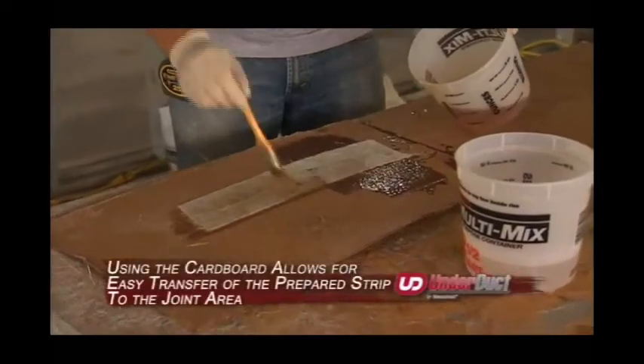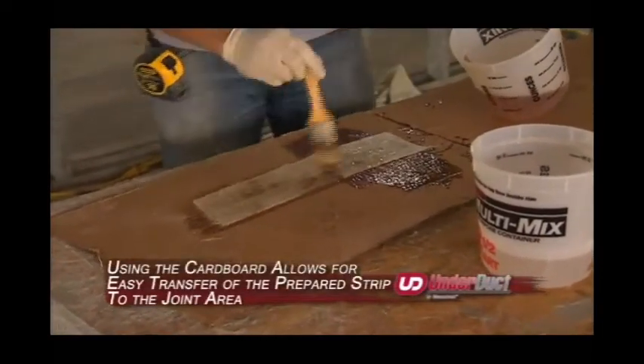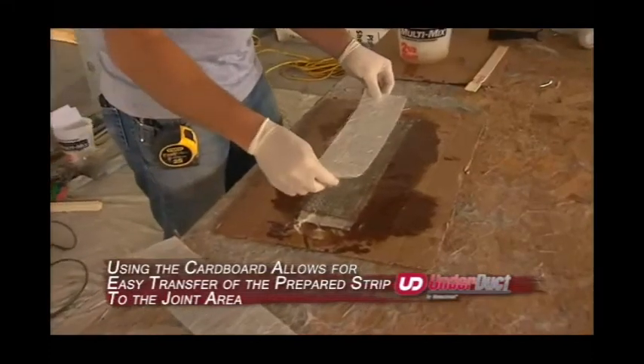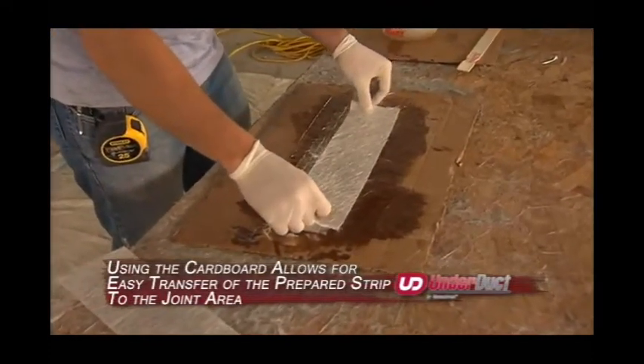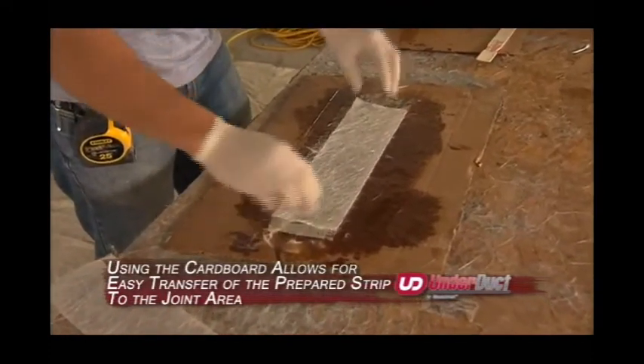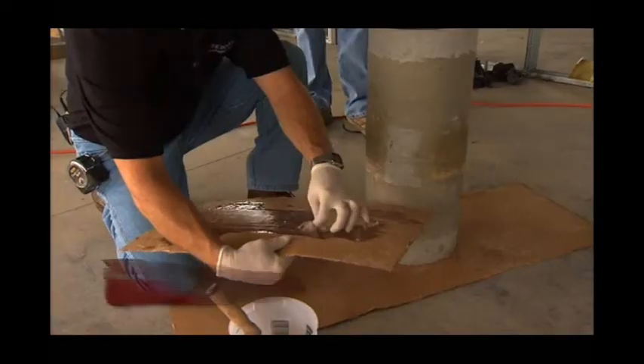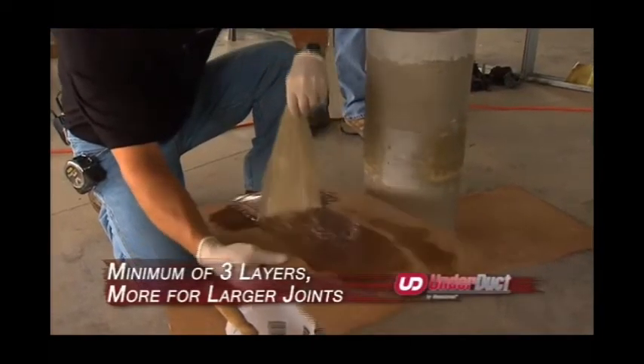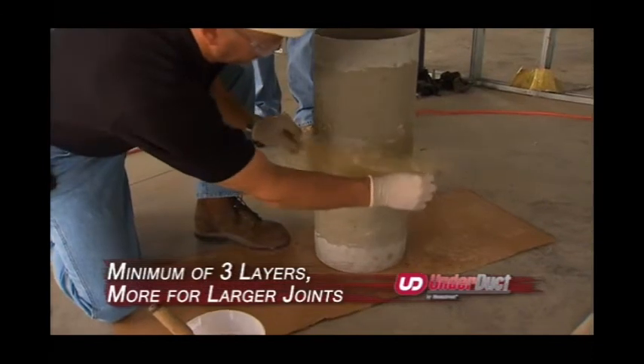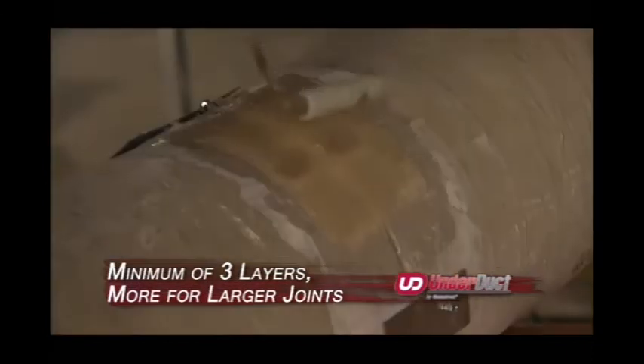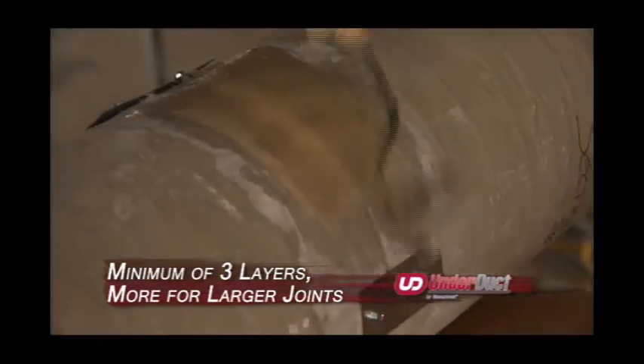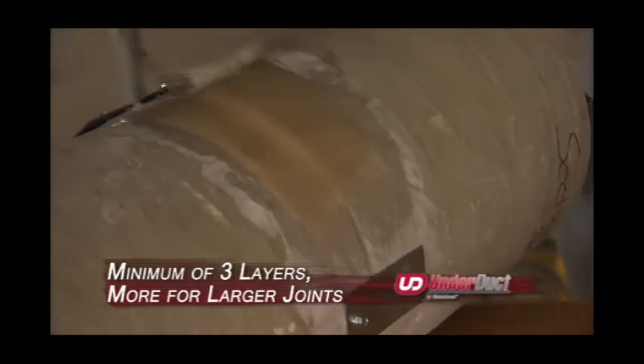Saturate 1 strip at a time on a pre-cut piece of cardboard, staggering the strips side to side and end to end until you have the recommended number of layers. Lift the completed weld strip or hot patch and apply to the pre-ground joint area. Using the hard roller, roll out all the air from the wet laminate.